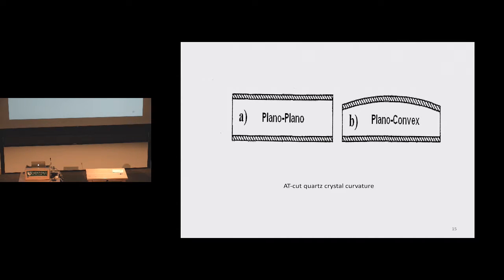Further than that, we went ahead and we fabricated that device, and we proceeded to characterize it, and we did not get the responses that we expected to get. We went back to the quartz crystal monitor and we began studying it very, very carefully, and what we found out was that the quartz crystal monitor did not have a bottom surface that was parallel to the top surface. In fact, one surface was like this, the other surface was planar convex.